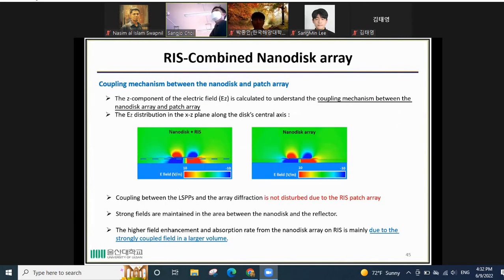And this is the coupling mechanism between the nanodisk and patch array. We analyze the electric field distribution along the z-axis. From this we can see that the coupling between the LSP and the array diffraction is not disturbed because of the patch array. We can also see from here that strong fields are maintained in the area between the nanodisk and the reflector. So from this we can conclude that the higher field enhancement and absorption rate from the nanodisk array on RIS is mainly due to the strong coupled field in the large volume.